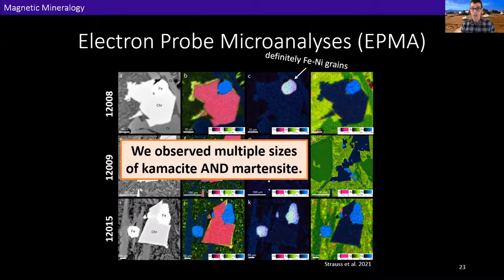We'd also been thinking about some studies that were published recently suggesting that association with troilite, which is an iron sulfide mineral, might be an indicator of good paleomagnetic fidelity in lunar basalts. But we went looking, and that's what's going on with this fourth column, where now we've got sulfur in magenta and iron in blue. And we didn't find any grains with compositions consistent with troilite. So in general, we would say that troilite may be forming through processes that also produce submicron iron grains in some lunar rocks, but it's clearly not a requirement in order for lunar rocks to have good paleointensity fidelity.